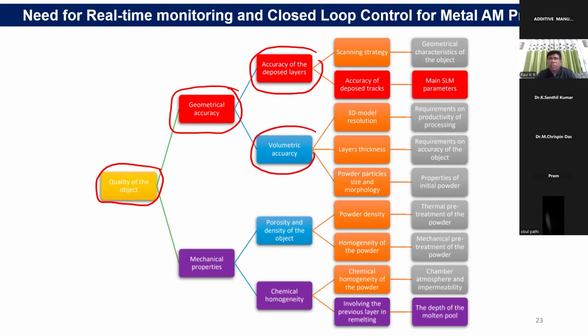Okay, this depends on what kind of scan strategy we use, accuracy of the deposited tracks, 3D model resolution, layer thickness, powder particle size. As I told you, the bigger the layer thickness, your accuracy would be lower. Again, the bigger the powder particle size and morphology, the lower would be your accuracy. In addition to that, the final part what you make should have a consistent mechanical property. It should meet the design requirement in terms of its outcome. The final product should meet what the design engineers really need, the component mechanical property.